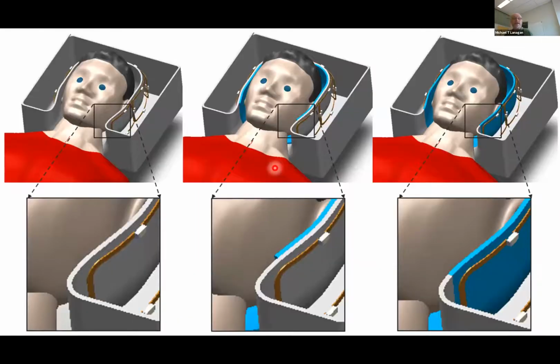One example of some designs we're doing, this would be an example of someone within the tube, and you can see here this little cutaway. We have the coil shown here, and what we're doing is we're designing these dielectric pads. This would be shown here in blue, where we basically can then couple electromagnetically more efficiently from the coil into the head and back again. So we could actually make the pad as a structural unit of the helmet as well. So this is some of the current research.